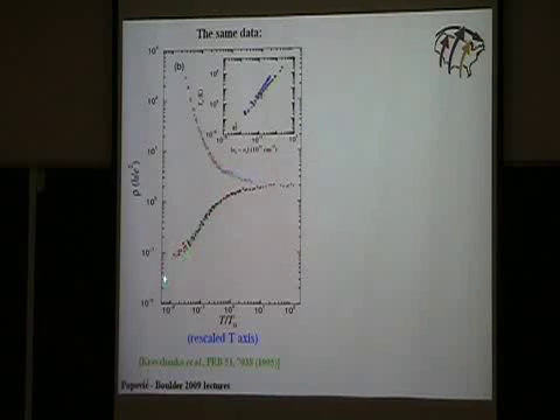So these are the same data. It's just that this axis is rescaled. What does this mean? It means that for each of these curves, for different densities, they divide temperature by some number until the curve shifts, and so they make all of them collapse. The number that they use for each curve, to shift each curve, is shown here as a function of density. So you see that on the metallic side and on the insulating side, all data can be described by the same function for different temperatures and densities. And this characteristic energy scale decreases in a parallel fashion.